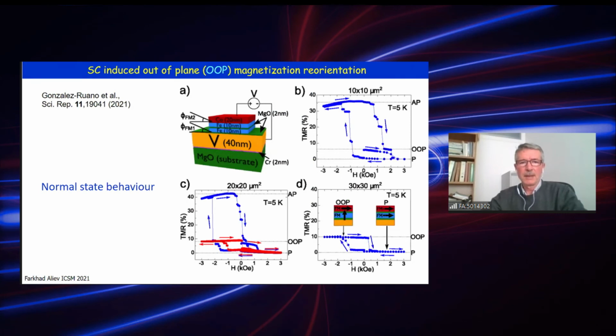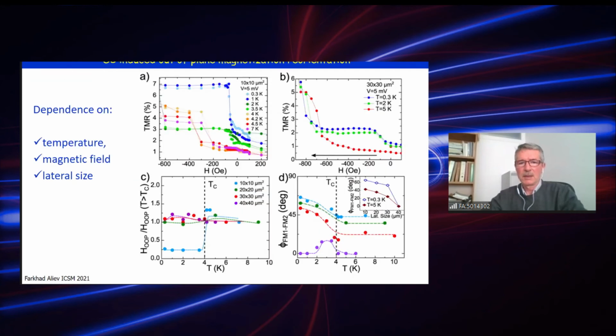Finally, we very recently showed experimentally another effect predicted by theory: that out-of-plane anisotropy could also be affected by superconductivity. For example, here you see that the out-of-plane field changes dramatically for the 10 by 10 sample, but for larger samples a bigger effect is seen, and we attribute this to competition between in-plane and out-of-plane anisotropy.